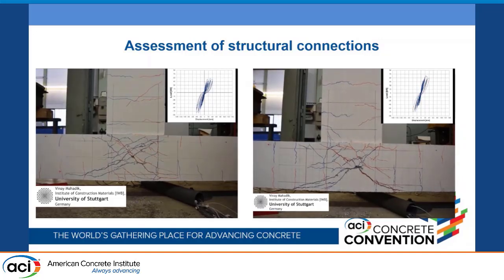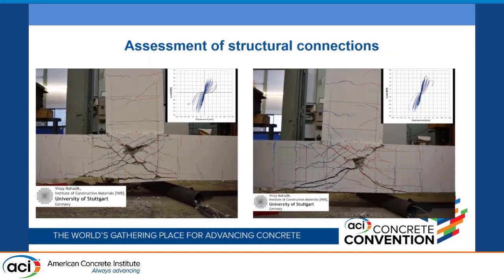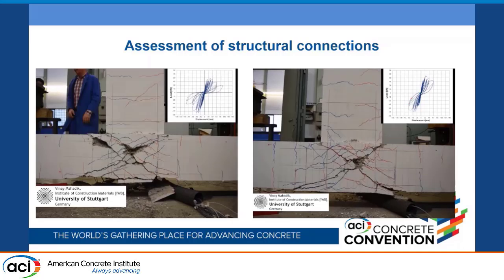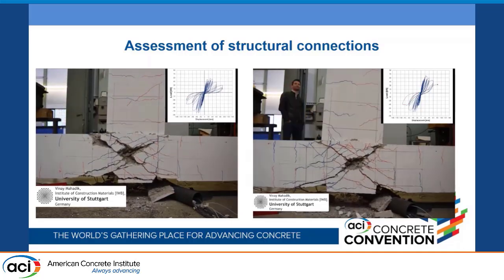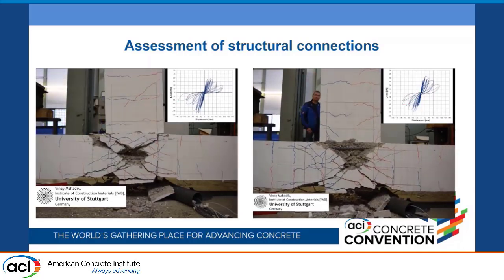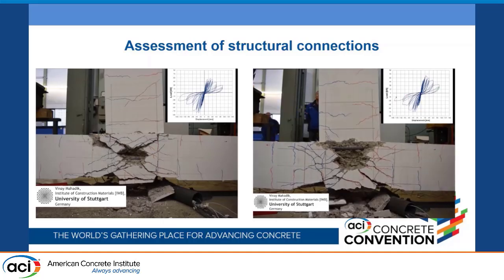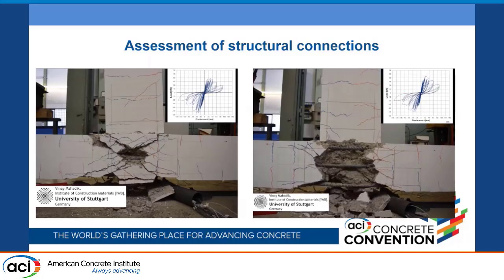So in the cast-in case, on one side the hook was bent in, and on the other side the bar was straight. And that's why we see this asymmetry in the results, but in post-installed, of course, we have post-installed bars on both sides. We see symmetric results, but the failure load is much higher than what we got in case of cast-in straight bars. We also did some tests with wall foundation connections. Sorry for this, I do not know why it's happening, but we can see the concrete cone breakout happening in case of wall foundation connections. We varied the thickness of the wall and so on.